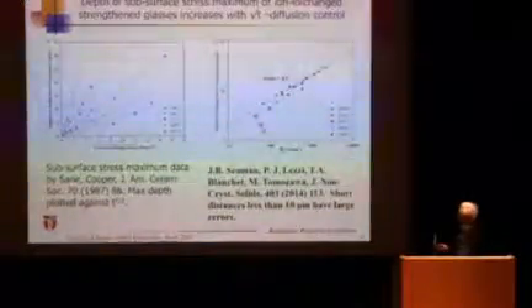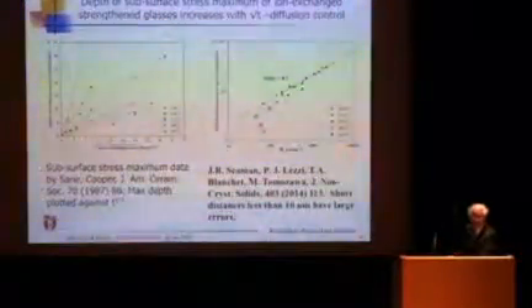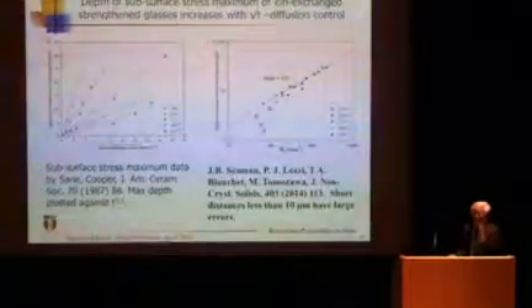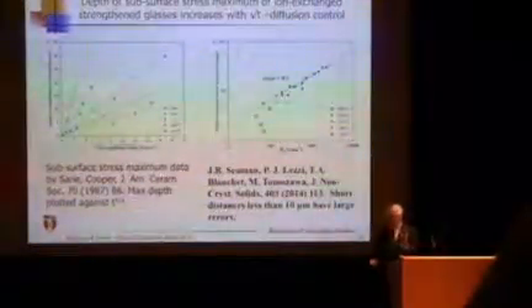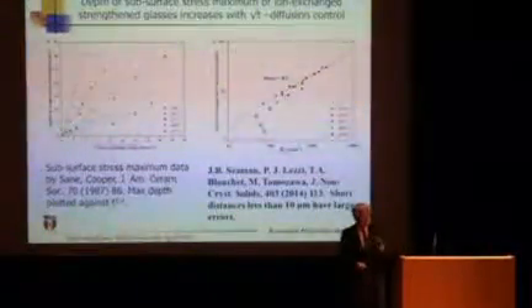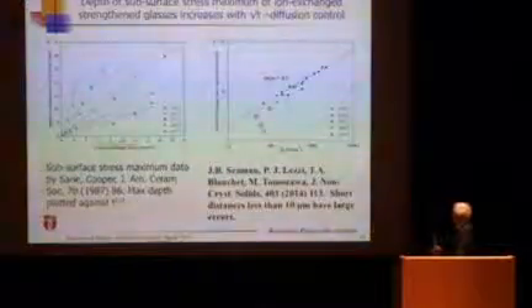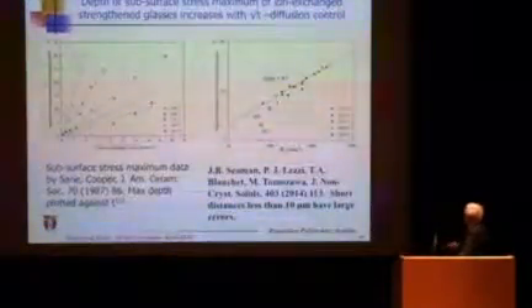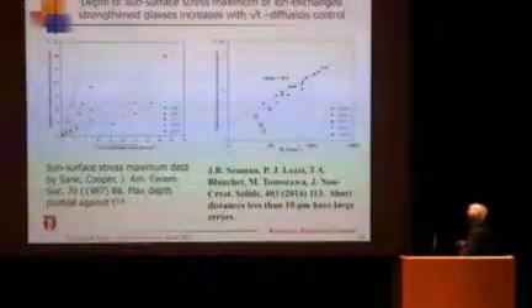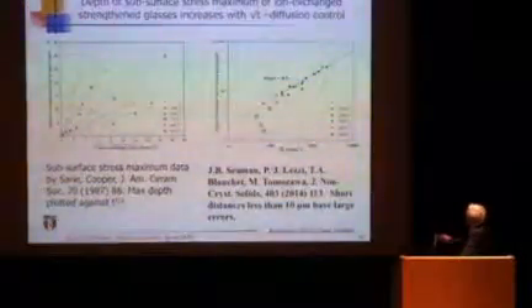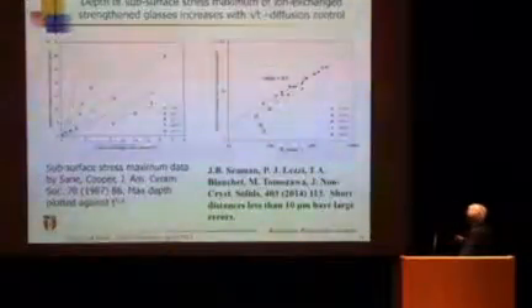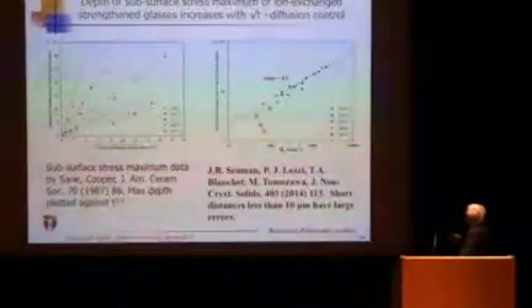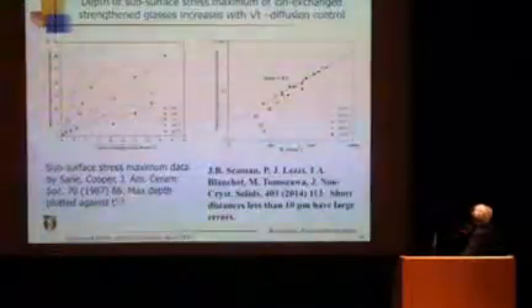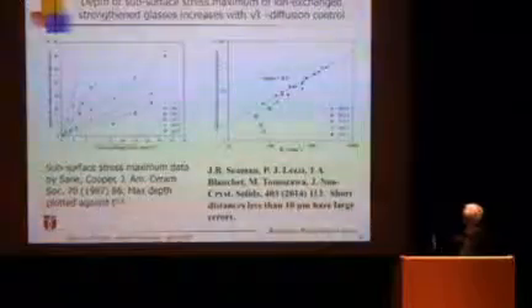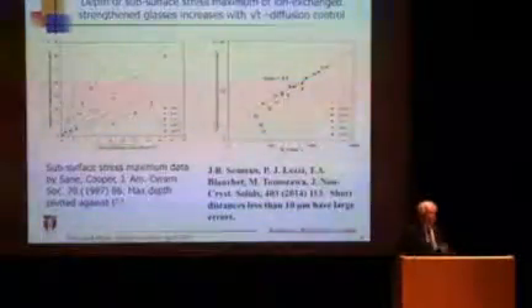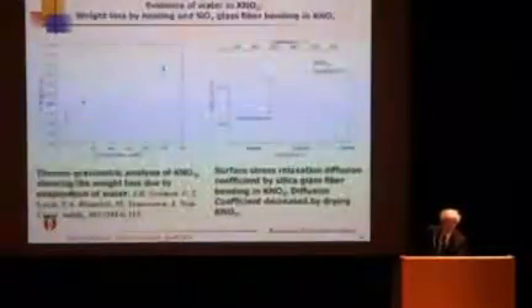What we thought is this must be due to surface stress relaxation. In other words, a small amount of water in the nitrate, potassium nitrate, may be causing the surface stress relaxation. So we plotted this data, other people's data, in a square root of t normalized fashion. This is the depth of the peak position, and except for the short time, which has lots of error because it is less than 10 micrometers, they follow a square root time dependency that suggests it's a diffusion phenomenon which is causing this surface relaxation.